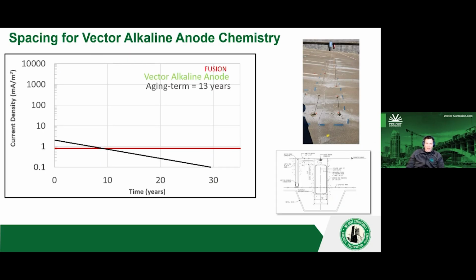So this is a vector alkaline fusion anode. The aging term is going to be increased compared to that pure galvanic option. And this is sort of what that aging curve looks like. Phase 1, a higher current output. And then once that's depleted, you get the galvanic piece at a much shallower angle, and you're going to get a much longer life than just purely galvanic.